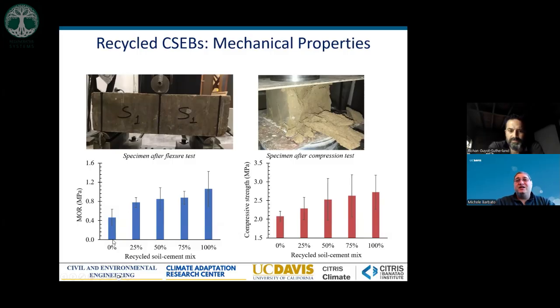And here you can see that actually what you get is a strength that increases when you use more recycled soil. The 0% corresponds to the original blocks made with only natural soil. Then 25, 50, 75, 100% is the amount of recycled soil that is used to reproduce new blocks. And you can see an increase both in the modulus of rupture and in the dry compressive strength with the increase of the recycled amount of soil in the mix.